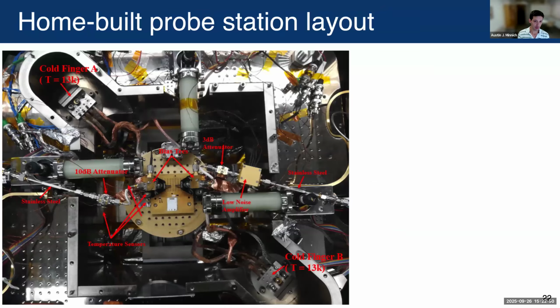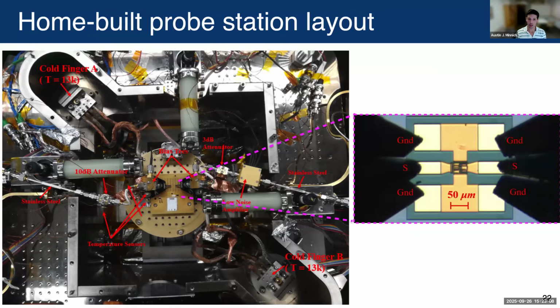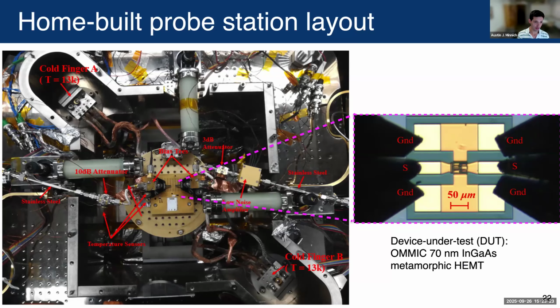So here's the picture of this is a home-built probe station in the radio astronomy lab at Caltech. It's a very busy picture, so you don't need to look at everything, but if you look towards the center of the picture, you can see the gold or brass colored locations. So that's where the device sits, and there's a blow up of a device on the right. This is an OMMIC 70 nanometer InGaAs metamorphic HEMT, which is the device under test. The signals come into the probe station from the left, and then they exit on the right.